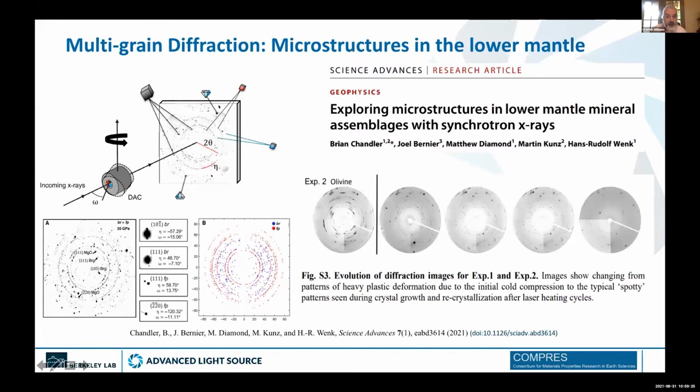So in this particular example, what's done here is to take olivine and convert it to its high pressure phases, magnesiowüstite and bridgmanite, and then deconvolve this mess of a pattern into all of the crystallites and their orientations, with the decomposition of olivine to perovskite and magnesiowüstite and its subsequent texture evolution. So in this instance, for example, a 110 twinning in perovskite was recognized, which may heavily contribute to the stress relaxation mechanism within this material.